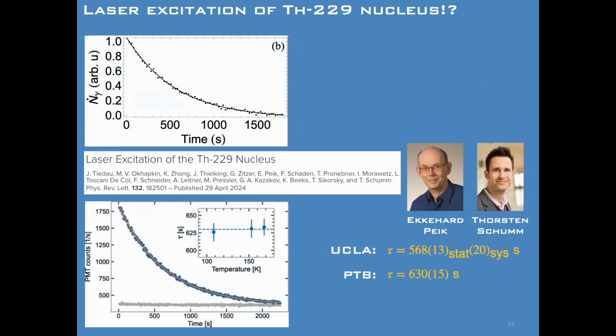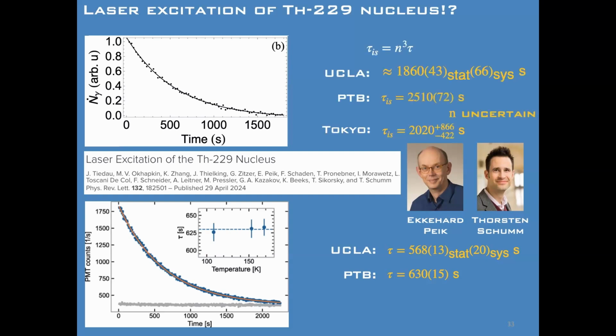They see a slightly different lifetime, but that's expected because the index of refraction of these two materials is different. In fact, they're using calcium fluoride, I should say, and that index is actually known pretty well, like NIST measures that. For our crystal, no one's actually done an accurate measurement of the index. We're working on that now with NIST. So these look pretty consistent with what's expected.